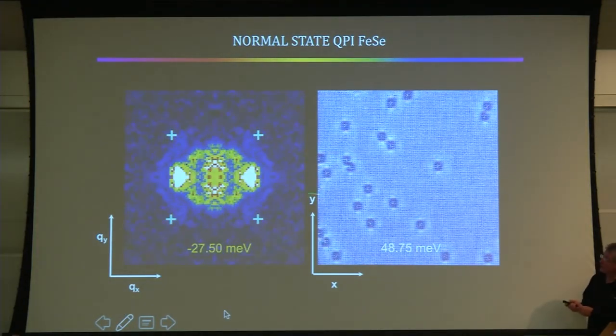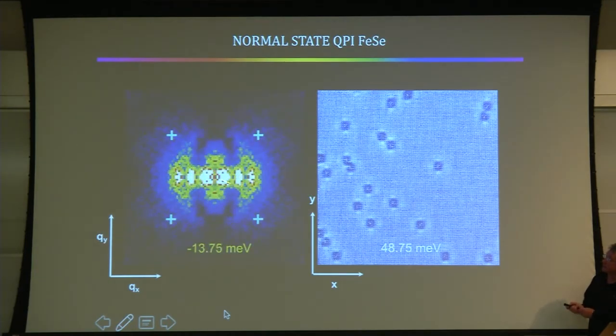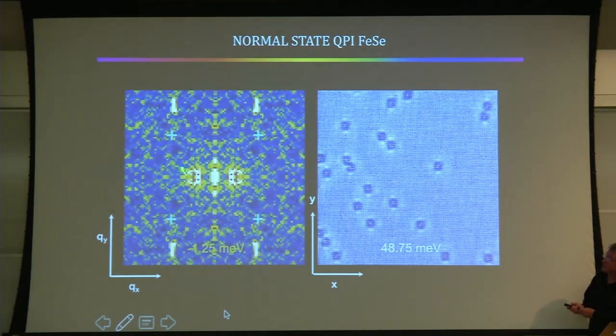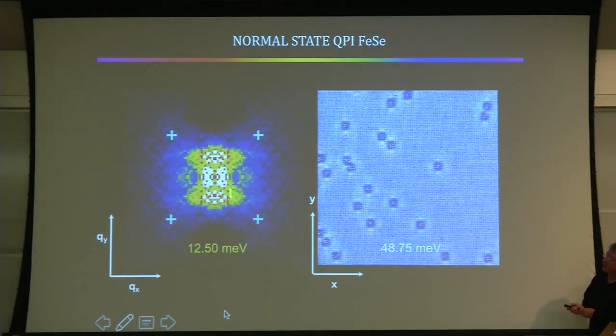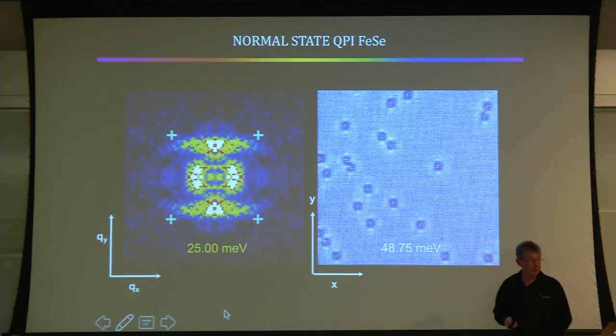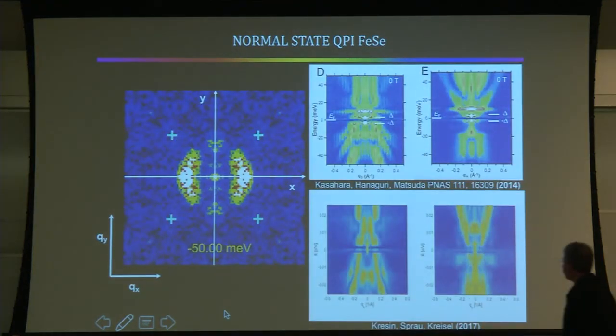It moves predominantly along this direction. This is the A direction of the orthorhombic crystal. But when it passes the chemical potential, it rotates, and then it moves predominantly along the other direction, which is the B direction. Very strange. It's not a technical mistake. Our very good friend, Tetsuo Hanaguri, had studied the normal state of this compound several years ago, and his data and our data are in very, very good agreement. It isn't a property of the experimentalist or the STM or the tip or the symmetry of the tip or the identity of the impurity or who grew the sample or anything. It's a property of the material.